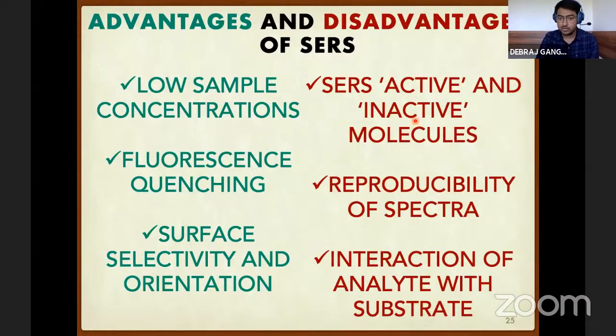Not all molecules will produce SERS spectra. Reproducibility is a big question in SERS spectra. You may not get exactly the same SERS spectra every time you record it because of the interaction of ANALYTE with the substrate. The ANALYTE may interact differently at different instances with the substrate, and thus you may not get the same spectra every time. So in order to improve the reproducibility, we try to improve the quality of the SERS substrate that we produce. And mostly we have seen that the thin film substrates produce better reproducible spectra than the colloidal substrates. Well, that is a different aspect, which I shouldn't discuss now. It will become too long.